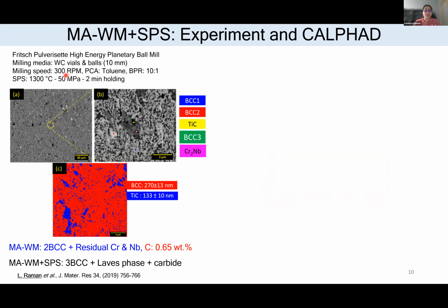So the ball milling was done at 300 RPM with toluene as the PCA in tungsten carbide vials. Once we have the powders, when we characterize them using XRD, it showed the formation of 2 BCC and some residual elements. We also tried to estimate if we have any contamination from the toluene or the milling media. Then we found we have this much amount of carbon.